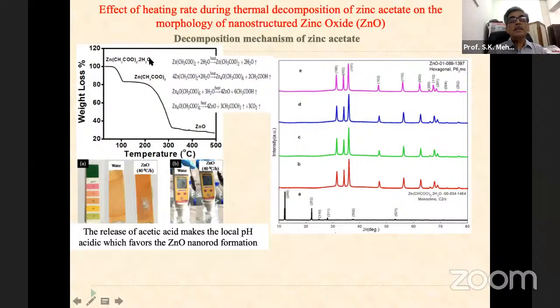You can see zinc acetate having some water. So the first step is to remove the water. We will create anhydrous zinc acetate, and in the next step, the loss is there, and you get the zinc oxide. Carbon dioxide will go, and zinc oxide formation. So this is a step how this takes place. We can say that you heat; in the first step, you get zinc acetate. Rearrangement takes place. In the third step, you have zinc oxide formation, and finally you have carbon dioxide which goes off. So this is a mechanism that we can understand.